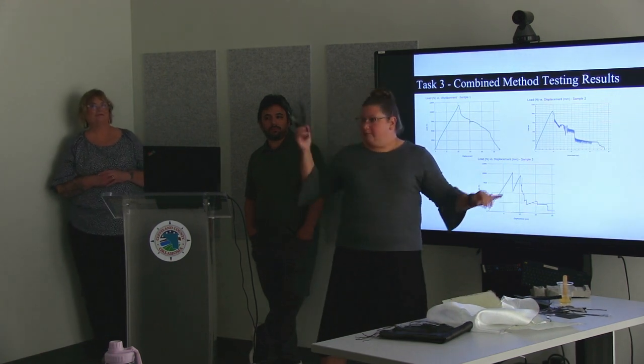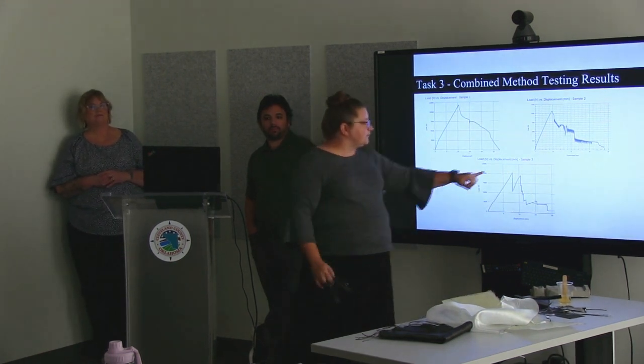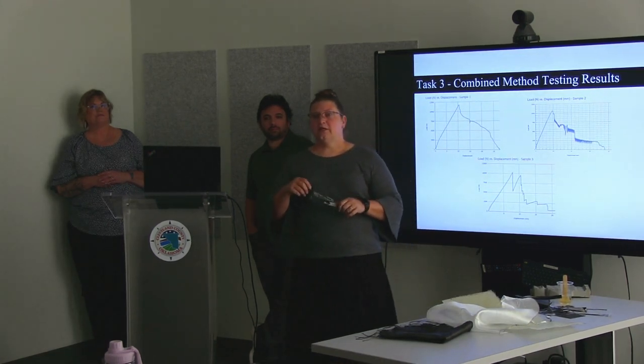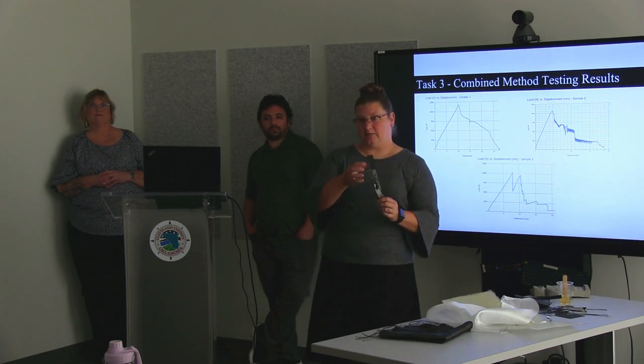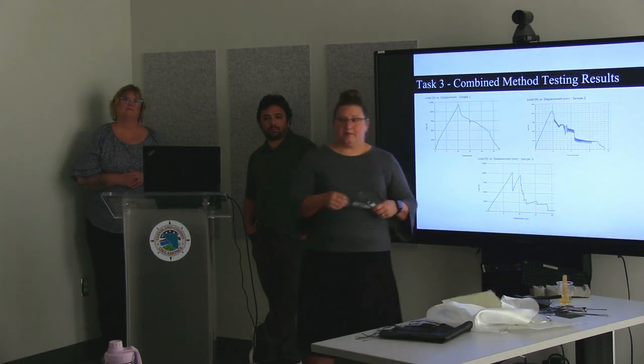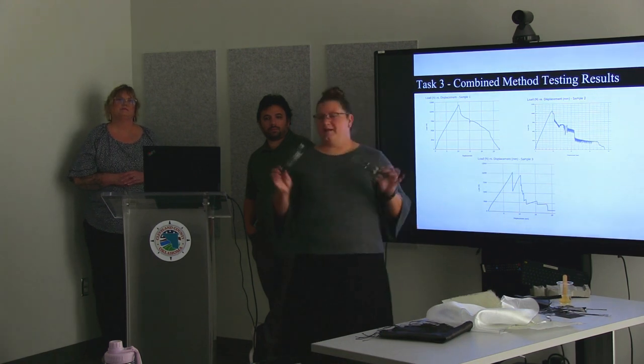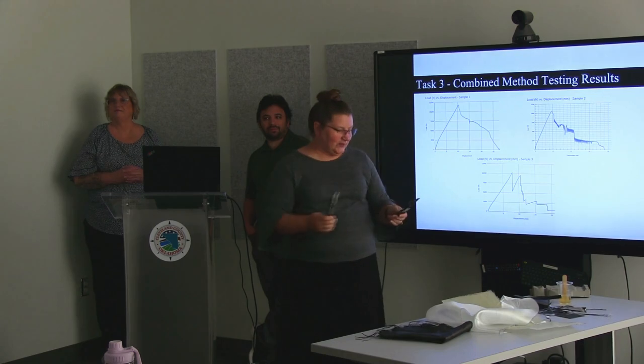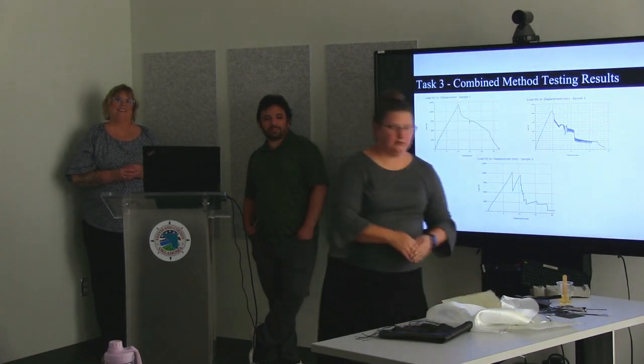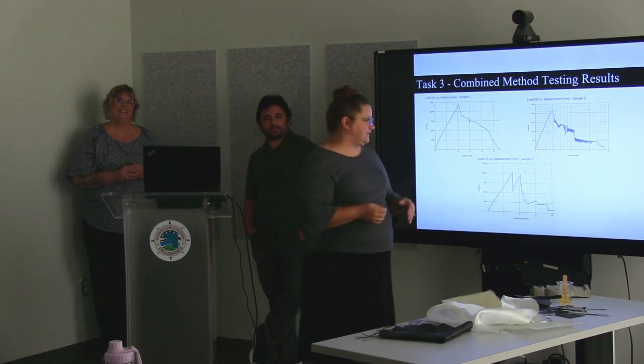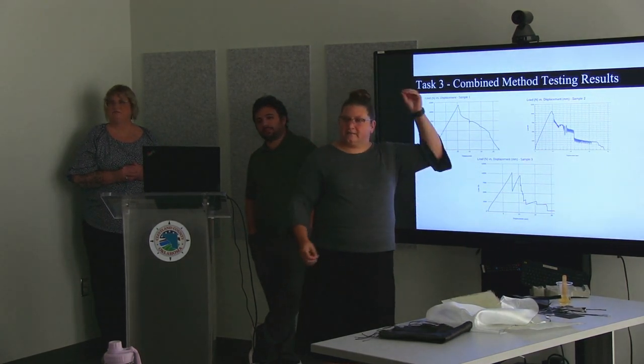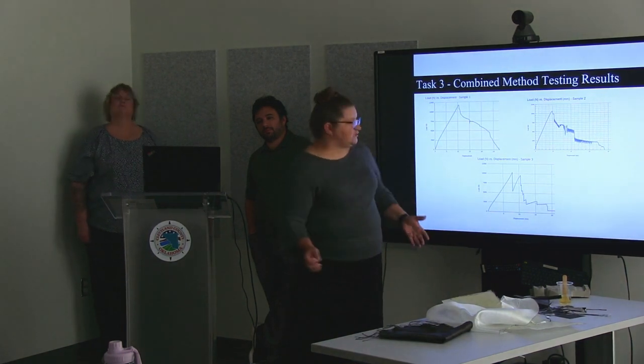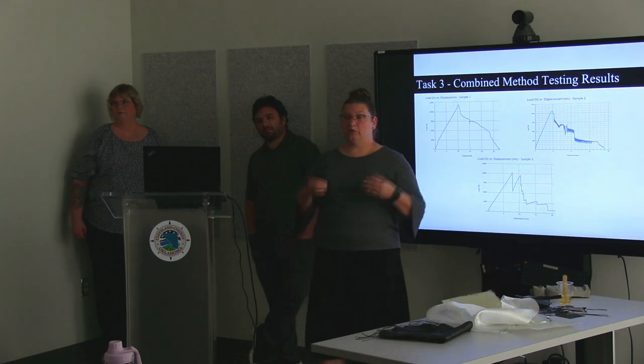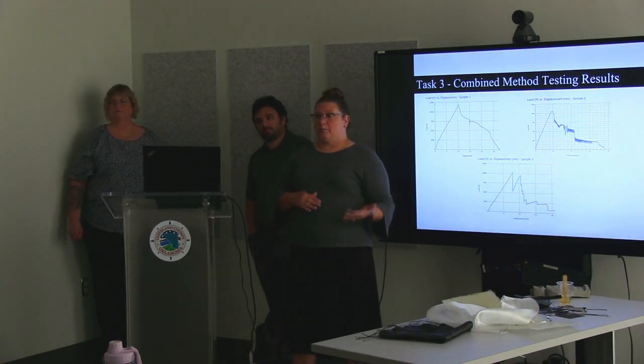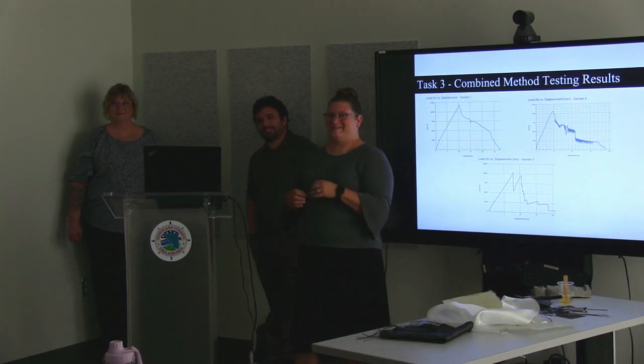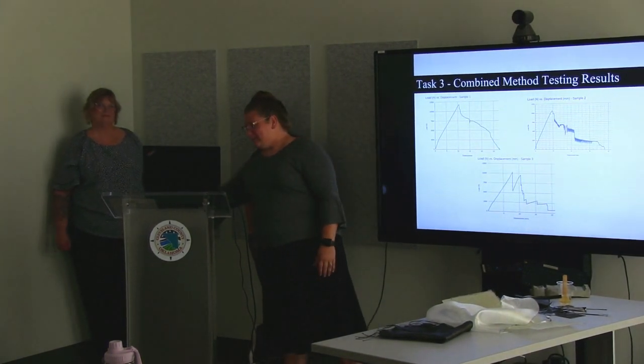And you can see the graphs that Bridget went over earlier. Once the first failure occurs, the forces are then transferred to the next one, and that's where it picks it back up. And so you can see that by our peaks and our fully destroyed sample. So it was successful, and then it was able to transfer the forces so it didn't have that catastrophic failure all at once. So it makes it safer, gives you a little more time to address the problem before it becomes an even bigger problem.